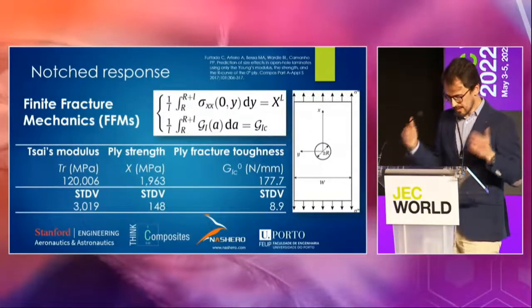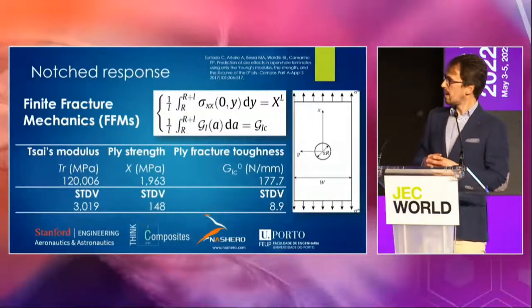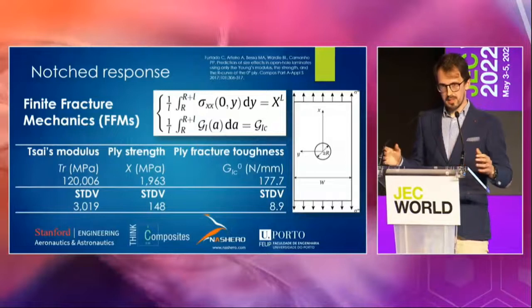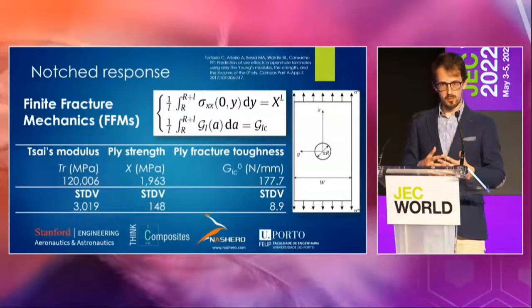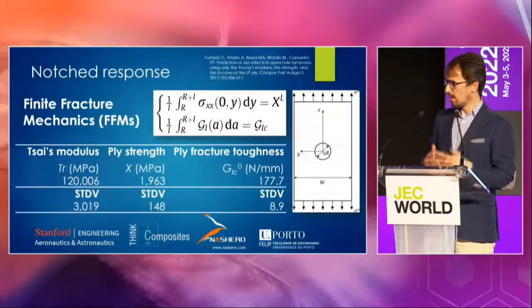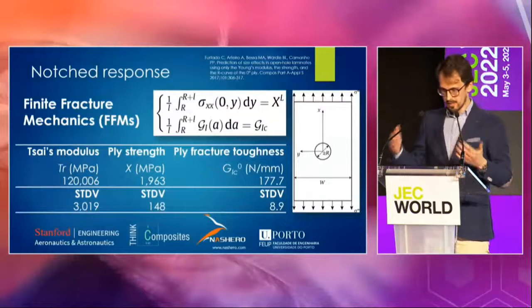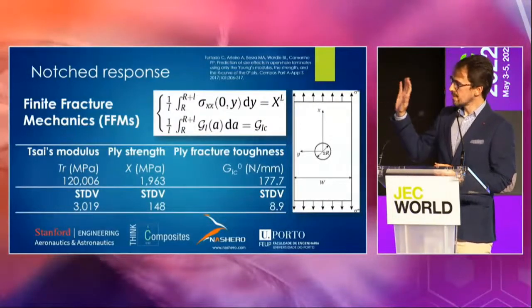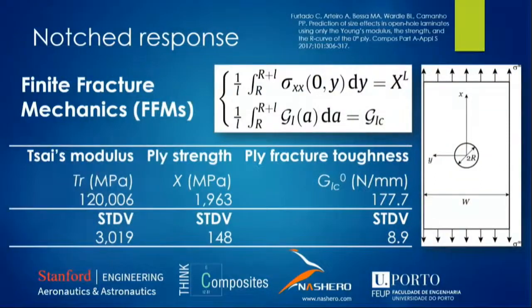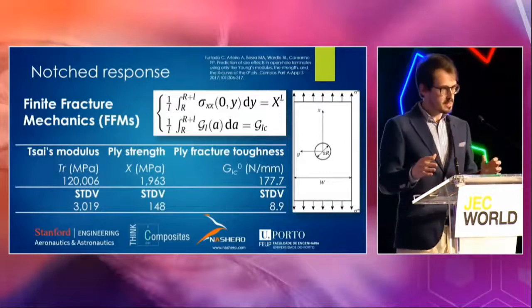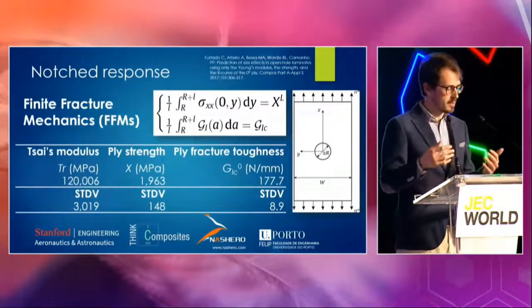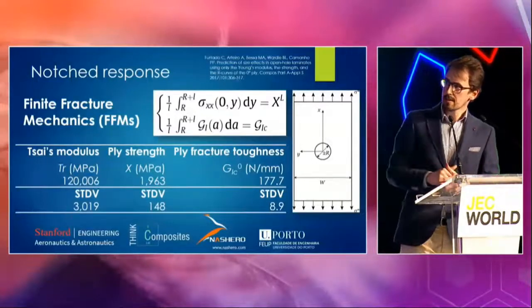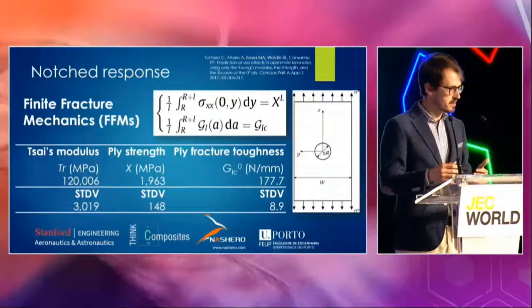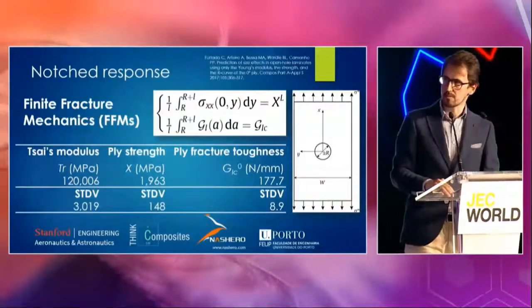To do this exercise, I take an analytical tool that has been applied and fully validated for notch tension and compression strength prediction of legacy laminates, and we'll be applying these in the context of double-double. So, as I said, it's a closed-form solution based on a theory called finite fracture mechanics. Essentially, you have to solve a system of equations where you have in the first line a stress equilibrium in the sense of an average stress criterion, and in the second line you have an energy balance in the context of finite fracture mechanics, or fracture mechanics in general.